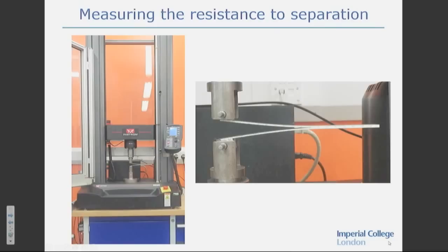And the test for doing that is shown here. This is an Instron test machine. It can apply tension loads to specimens. This will apply up to 50 kilonewtons. And we've got a specimen in here to measure this resistance to separation. Here's an enlarged view of it. The specimen's connected to the test machine at these points, and here it is. And all it is is a composite specimen in which we've already separated the laminate at the midplane over a certain length. Then the test machine pulls the laminate apart.